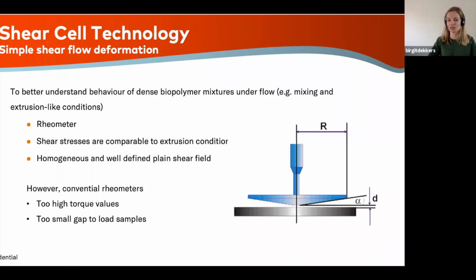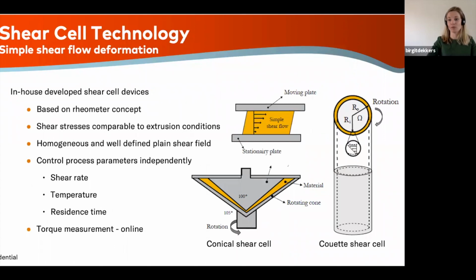However, as soon as you put a more dense biopolymer system into a rheometer, you are challenged with high torque values or higher viscosities, such that you reach torques that you are not able to measure with a conventional rheometer. Often what we also saw is that the gap is basically too small to load your sample, and therefore all the types of measurements that you try to do are difficult or even impossible. For interpretation, it's for sure not possible, but also even just simply measuring it in practice was difficult. And therefore, the idea came up to develop our own rheometers that were able to do these kinds of things.